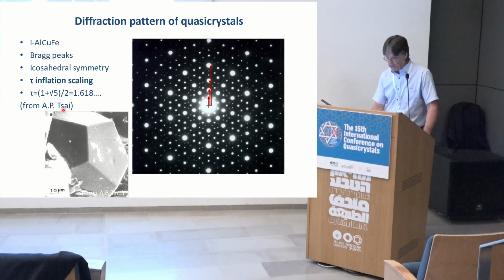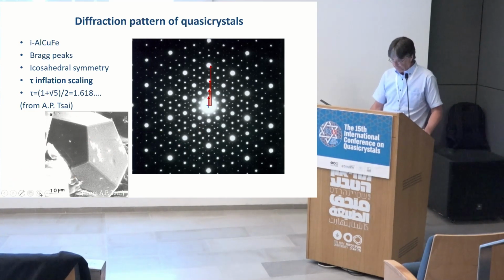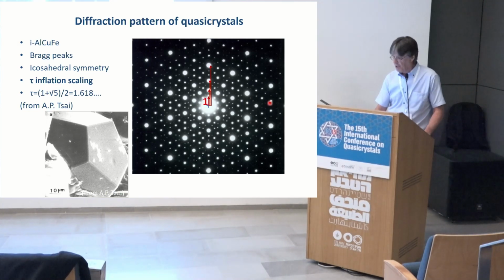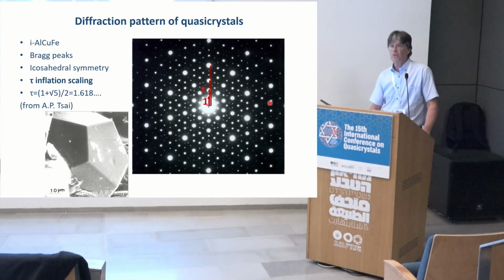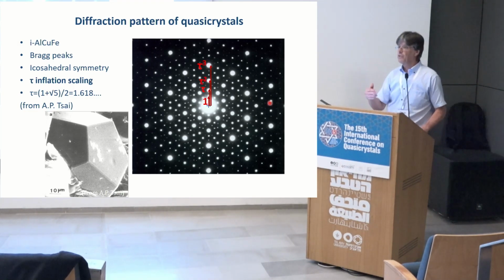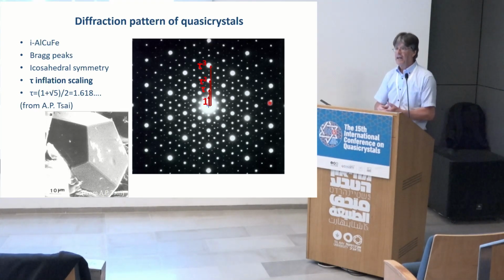This is aluminum copper iron, provided by A.P. Tsai. And if I look, besides the tenfold symmetry, at the ratio of the length scales I can see between the strong bright peaks, I see that if this one is 1, then I have tau, where tau is the golden mean, an irrational number, then tau squared, tau to the power 3, and so on and so forth. So again, we have two length scales and a kind of self-similarity.